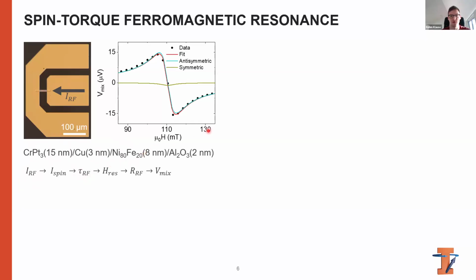And then we sweep the magnetic field through the ferromagnetic resonance of the permalloy film. At resonance, the magnetization oscillates at the same RF frequency that we apply to our sample. And this oscillation generates an RF resistance due to the anisotropic magnetoresistance, which mixes with the RF current to get a DC mixing voltage, which is what we measure here in this plot.